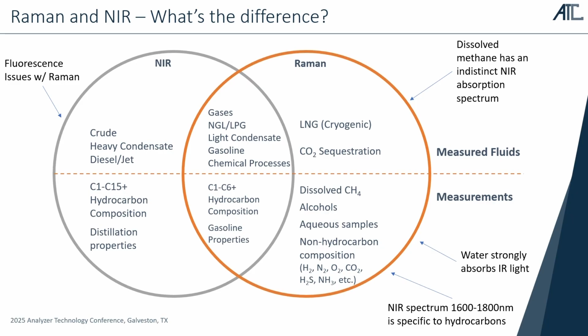And then for Raman, an interesting thing about liquid phase near-infrared spectroscopy is that dissolved methane has a really indistinct infrared spectrum. Methane itself has a well-characterized infrared spectrum in the gas phase and in the liquid phase. But methane dissolved at less than 1% has just a really indistinct infrared spectrum. And that's just not the case for Raman. It's a different technology, so you can see it just fine. So for something like natural gas liquids or Y-grade fractionation, where you're looking at demethanizer bottoms, for example, and you care about the percentage of dissolved methane, that's a great application for Raman, where with an NIR analyzer, we'd probably want to vaporize that sample. So that's where Raman makes sense.